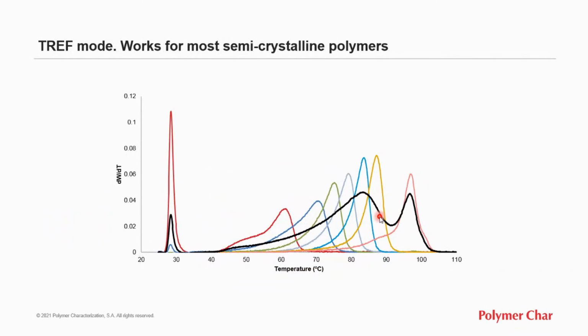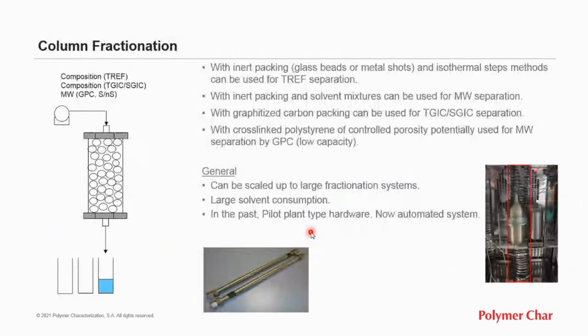The TREF mode is performed at increasing temperature steps, and it works well to obtain fractions of different chemical composition. We see here in black color the TREF analysis of the parent sample, a broad distribution polyethylene sample, overlaid with the analysis of the different fractions taken at different temperatures. They are narrower distribution fractions.